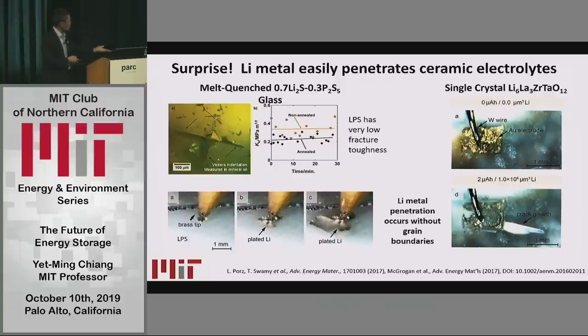In each case, what we're doing is, with the lithium, you can't see the ions, but they're coming through the solid, and it's plating lithium metal, and what you see is that you have this metal that's growing into the solid. That's what these pictures are showing you.